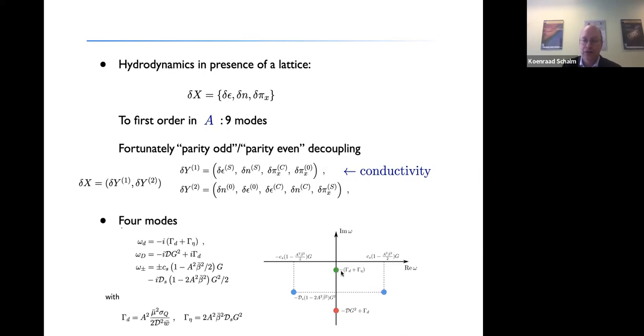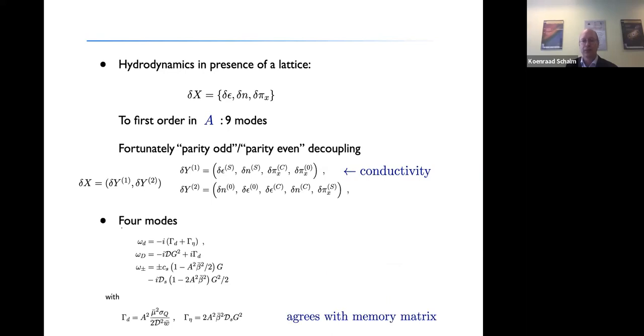Then there's the ordinary diffusion pole that was here, but there's also an Umklapped copy of the charge diffusion mode that I had earlier. And these are the 4 modes that survive in the system. And the 2 modes that I was talking about earlier are essentially these 2 modes where I zoomed in and dropped the 2 sound modes of the system. So this is where this extra mode comes from that I saw in this earlier picture.